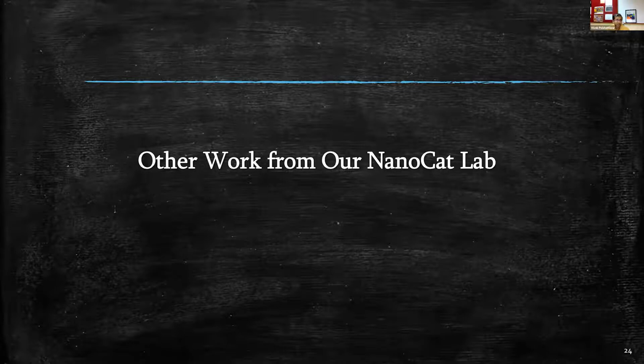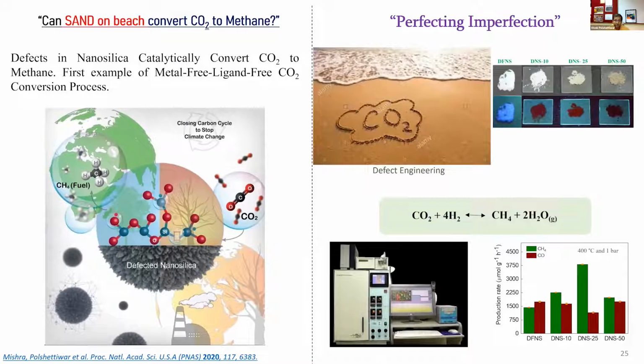in our lab. So this is one of the materials where we created defects in the silica, oxygen vacancies in the silica, and then the oxygen of the CO2 sees that oxygen vacancy, goes and sits, and then there are Si radicals and O radicals, which will then activate the CO2 and dissociate the hydrogen. So this is one of the metal-free catalysts that one can use.